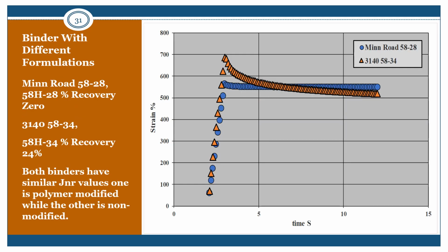And just to show you a little bit why there's a difference here, two different binders. One's a 5834 and one's a 5828. I picked these two because they have similar high temperature grades, but they're very different. You can see that in the creep and recovery response. With the 5834, when it's loaded, it has a higher deflection. But then when the load is removed, you have that recovery, giving you that delayed elastic response, showing you have some kind of polymer modification. But even so, they both end up in about the same place, which is, in the end, what we want to address rutting. But this shows you the clear indication that the polymer modification is something different.